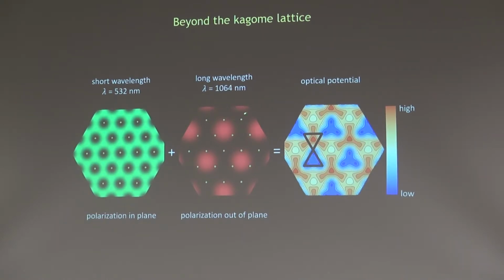And if we position things right, we can place these bowls in the potential right in between 3 sites of the original triangular lattice. And this new configuration distorts the green lattice in 3 ways. One is, like before, it takes one of the sites within the unit cell and pushes it up in energy, so it's excluded from our problem. So the remaining sites are Kagome-like in their geometric arrangement. But secondly, this infrared light also creates a little bit of a potential well between 3 sites within one of the plaquettes, let's say the plaquette pointing up, and then also introduces a little bit of a potential hill between the downward pointing plaquette within the Kagome lattice. So it breaks the symmetry that we used to have in the Kagome lattice between, let's say, the up and the down pointing triangular plaquettes. A third thing it also does is it causes the lattice to breathe. So it stretches the sites of the down-pointing plaquette outwards and the sites of the up-pointing plaquettes inwards.